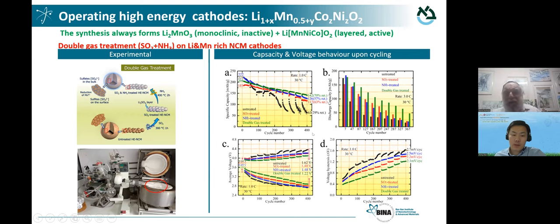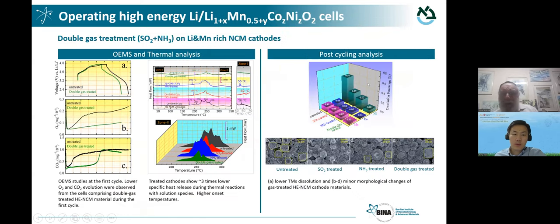You see here results over 400 cycles. And this is at very high rate. This is at 3C rate, at 30 degrees C. And we see that all the parameters, the hysteresis, capacity decay, voltage decay, everything improves thanks to the surface treatment. And as I mentioned before, whenever we have such stabilization, whenever we study cathode materials, we use as many channels of information, as many analytical tools as we can.